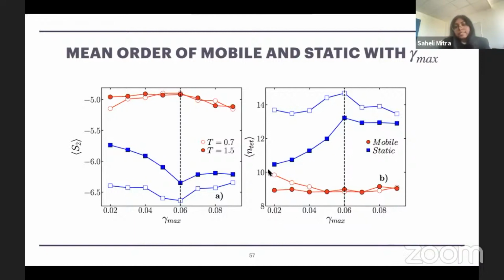For the static particles, with annealing, the structural order increases, and above yielding, the curve flattens out. Now, above yielding, the static part is actually the part belonging to outside of the shear band, and the mobile part is the part inside of the shear band. We'll see what happens in the presence of the shear band shortly.